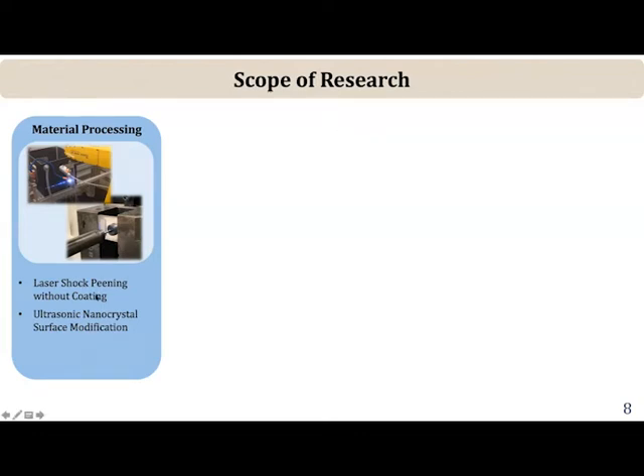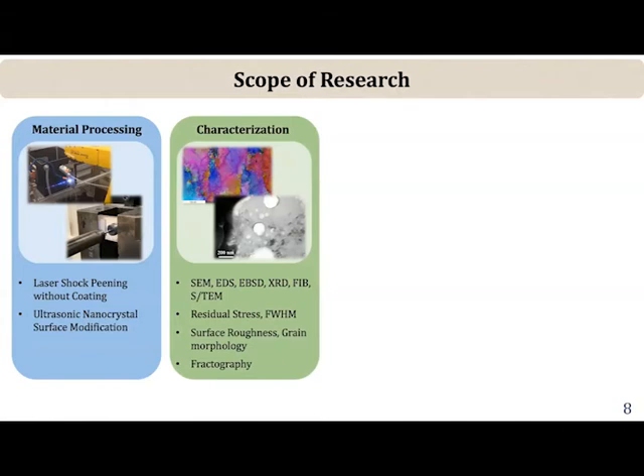One is laser shock peening without coating. Although Anurag has also looked at the effect of LSP with the ablative tape and then compared it with without coating. And then the UNSM ultrasonic nanocrystal surface modification technique.